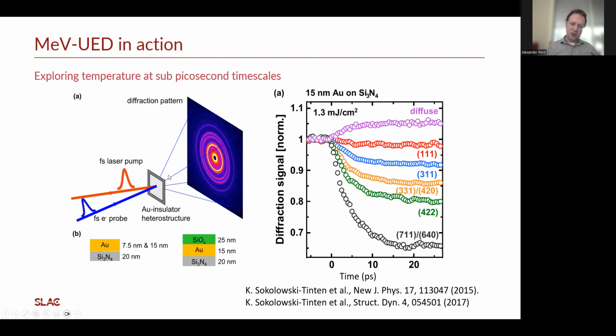These were placed into our beam and pumped with a femtosecond optical laser pulse. This optical laser pulse is coming into the gold and being absorbed via the conduction electrons, so this energy is going into those conduction electrons. What we're interested in this experiment is how that energy transfers into the lattice vibrations, into those lattice degrees of freedom. And this we probe by using a femtosecond MeV electron pulse in the transmission geometry that is timed to this laser pulse. And so this is our very typical pump-probe experiment.